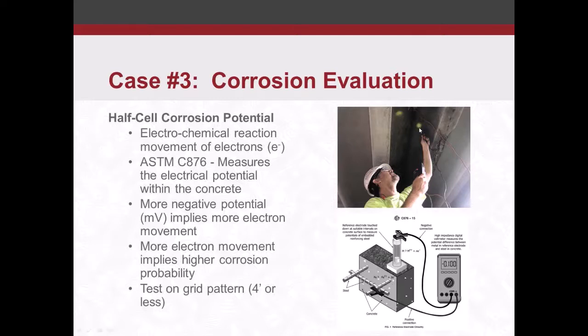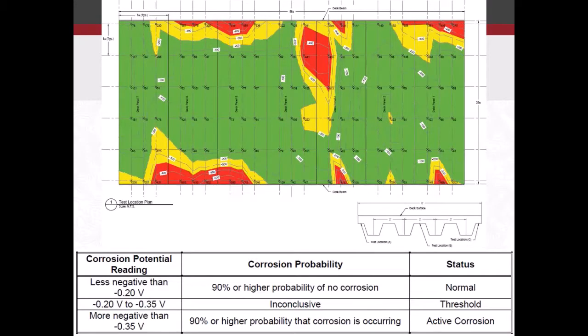So here again, we had to do it on the underside, because on the top side, you have to have electrical continuity between the concrete and the reinforcement. Well, if you've got an asphalt overlay on your concrete, or even any kind of epoxy overlay or something like that, you don't have that electrical continuity. Also, this doesn't work on coated reinforcement or galvanized reinforcement. There's different schools of thought there, but generally speaking, it's really not applicable to galvanized reinforcement either. But we're exposing the rebar, and we're checking the electrical potential. We do that on a grid pattern.